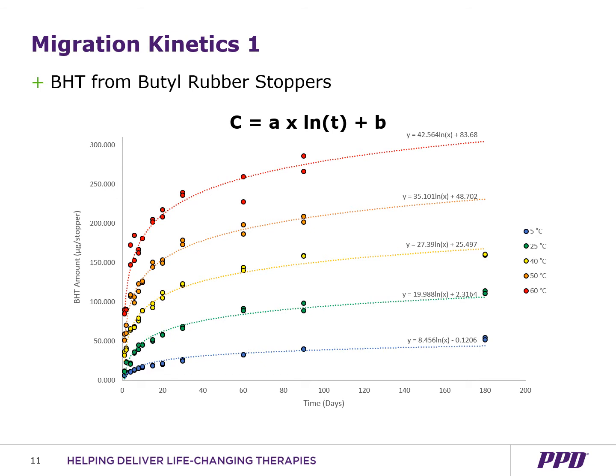I will point out that in this plot, most of the data goes out to 180 days, while for the higher temperatures of 50 and 60 degrees C, you will only see it out to 90 days. And that is because we observe significant degradation of BHT at those higher temperatures out at 180 days. And we are still working on characterizing some of those degradants to fully plot out the total amount of BHT in the degradants. And that is why you don't see that data plotted here.